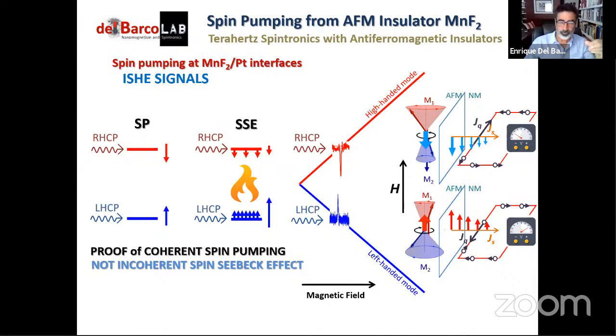And that gradient of temperature is gonna result in a charge current. But that charge current is actually coming from magnon modes from the state that is most populated. So whether you heat the high frequency mode or the low frequency mode, the result is heating. And as a result of heating, the spin Seebeck effect will generate spin current from the state that is most populated. And this is always the ground state. So the signal will always be positive. And if we see the observation of a reversal of the signal, it is a really good proof of the fact that this is coherent spin pumping instead of the spin Seebeck effect.